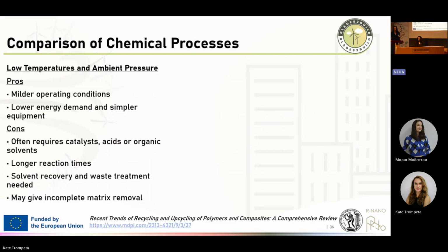So to compare these two processes, the low temperature and the high temperature solvolysis, the pros of the low temperature is that we have more mild conditions. That's why it's called low. It says already in the name. We need a lower energy demand and a simpler equipment. The downside to this solvolysis is that it often requires catalysts or acids or alkaline environments, longer reaction times, and then the solvent recovery is more difficult. And lastly and most importantly, it does not dissolve the resin correctly, and it might give an incomplete result for our fiber reclamation.